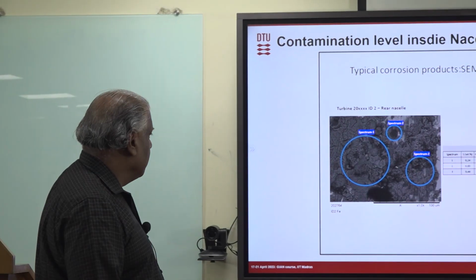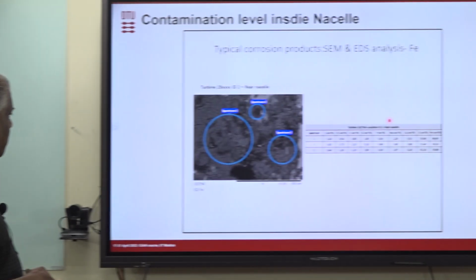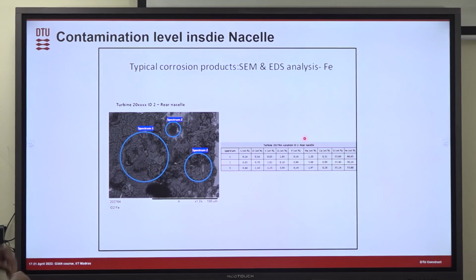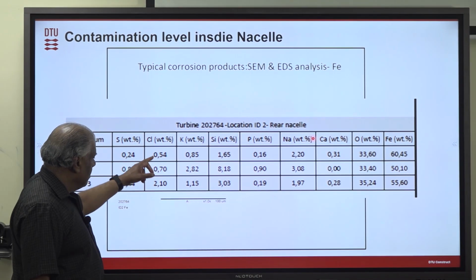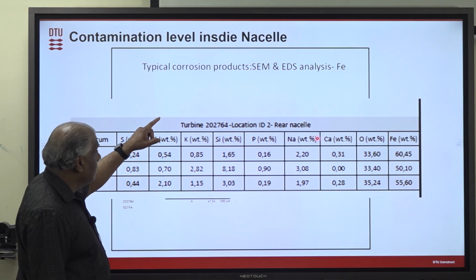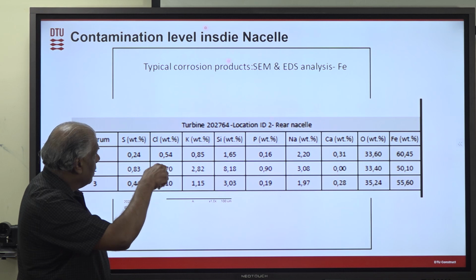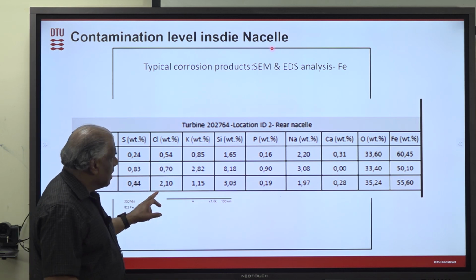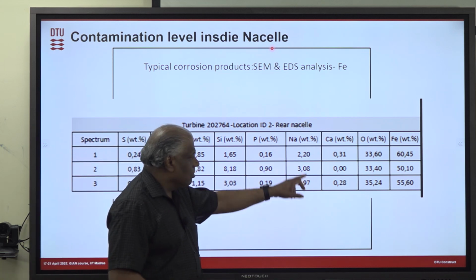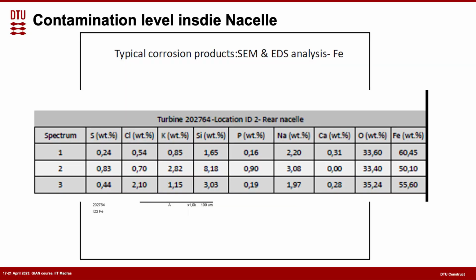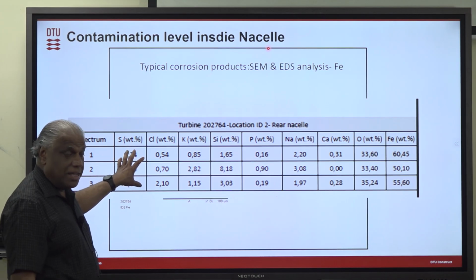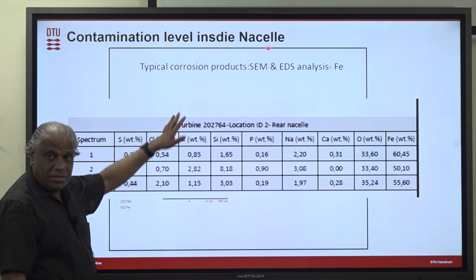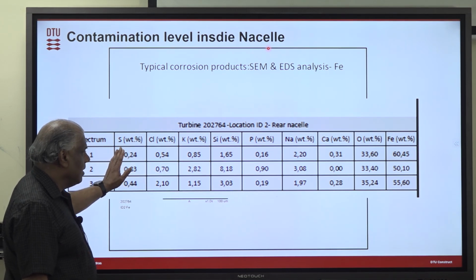We analyze the corrosion product, then we do the SEM analysis on the corrosion product. The important thing to show here is that it has chloride. This is coming from inside the nacelle; there's a spelling mistake there. It's inside the nacelle, and you can see there is chloride and there is sodium, which also shows that this must be sodium chloride. So although the air is filtered, some aerosols are still getting into the turbine, and that is probably causing this chloride to be there. You can also see a few other things. There is sulfur. So probably the reason is that there are some sulfur gases in the environment which also entered the nacelle and created some sulfur-containing compounds.